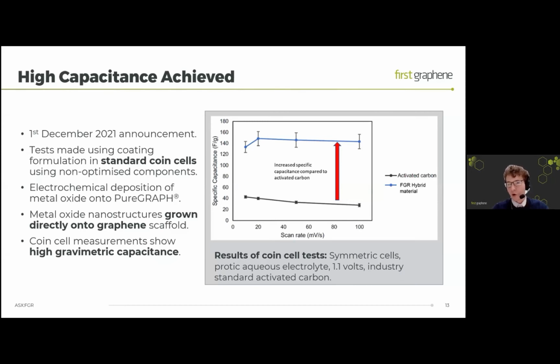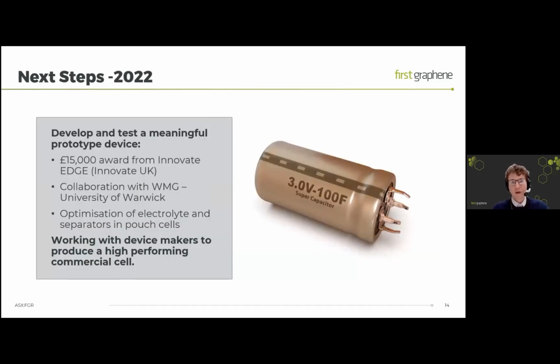The nanoparticles were grown on the surface of the graphene, and then used in the slurry formulation, and we got high gravimetric capacitance for these materials. So what do we do now that we have these materials? Well, our aim for 2022 is to develop and test a meaningful prototype device. So we have received an award from Innovate Edge, and we're really excited to use that with the University of Warwick at WMG, and we'll be optimizing the electrolyte, we'll be optimizing the separator, and we'll be demonstrating a pouch cell using these materials. And we'll be continuing to work with device makers to produce a high-performing commercial cell.